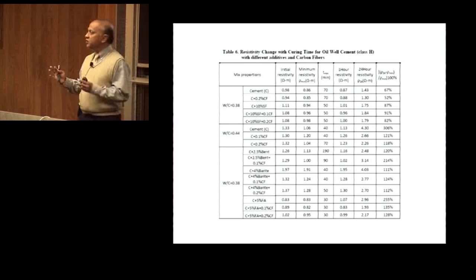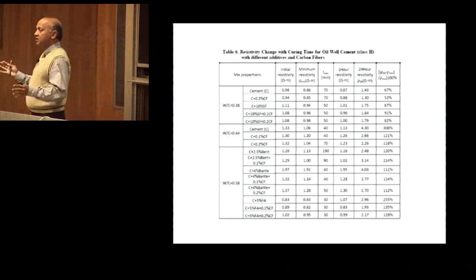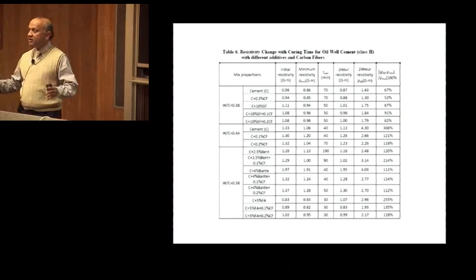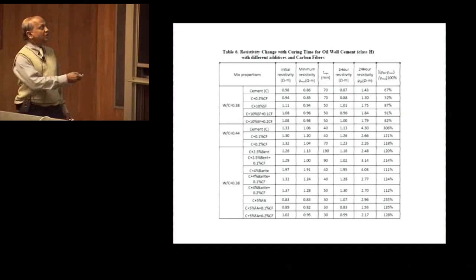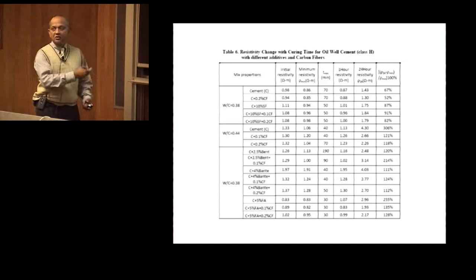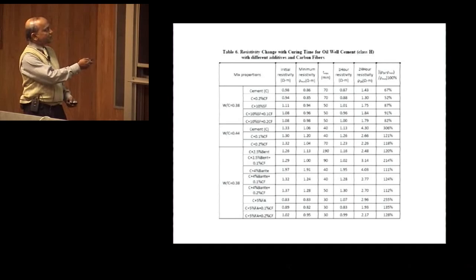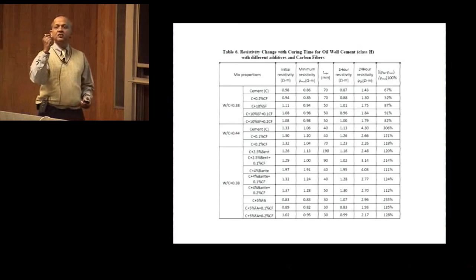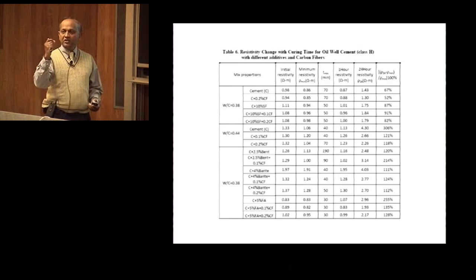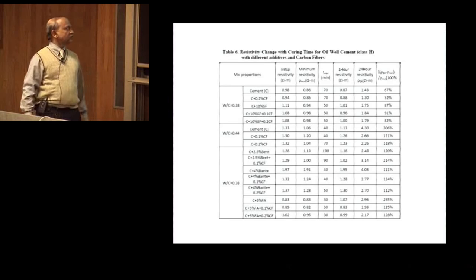So this could be used in the field as an indicator of, for example, is it setting or not setting? Just simple numbers, and you can see that in this case, you get big changes depending on the cement mix, depending on the contamination. We will talk about some of them, but you can see how sensitive the resistivity is to the changes, very sensitive to the changes.